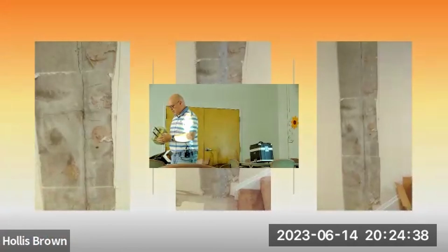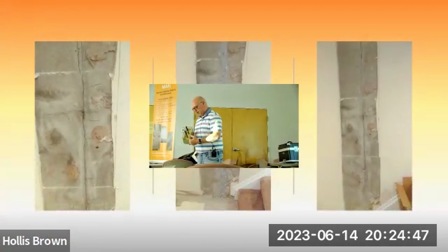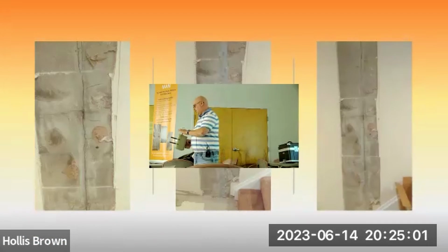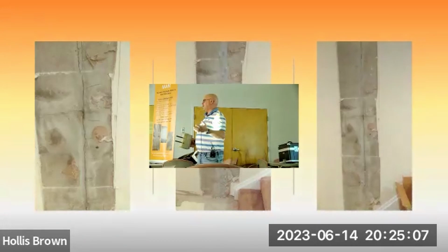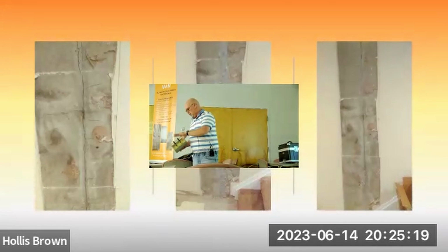As you can see, if this is the inside of the wall and this is the outside, the urethane goes all the way through, comes to the outside, and fills up the crack, and it encapsulates the rebar. Before this was repaired, water was coming in, hitting the rebar, you have some moisture, some oxygen, and it starts to rust right where that crack is and weakens it. I don't tell people, hey, your house is going to fall down if you don't inject this, no scare tactics like that. But you want to give everything a fighting chance, if possible. So it is an added benefit to inject this to prevent the rebar from rusting in the future.